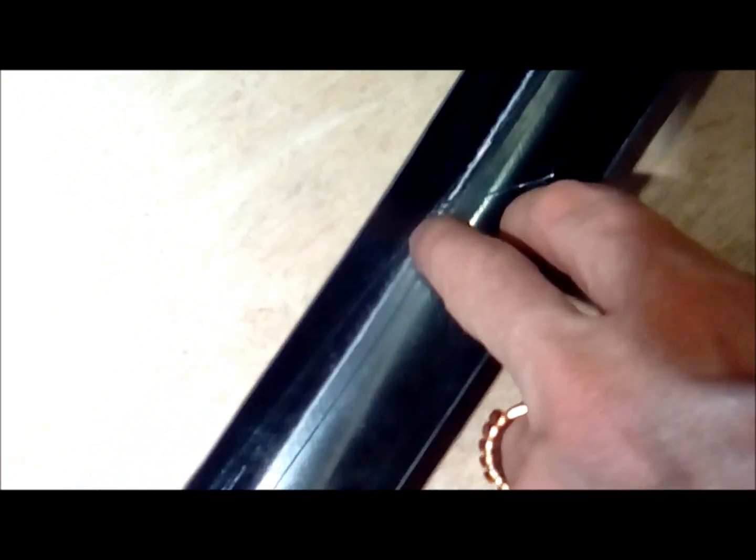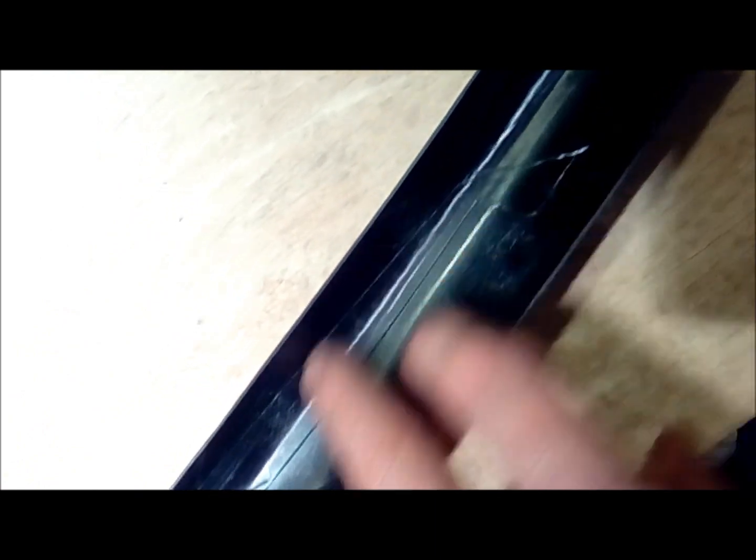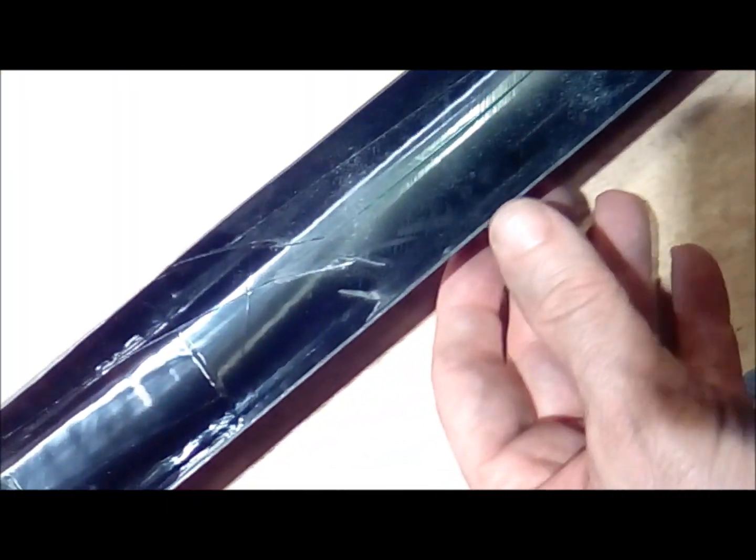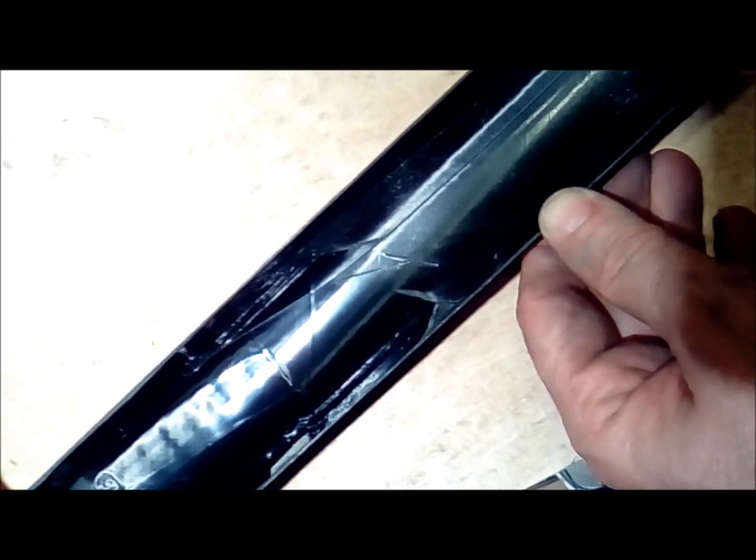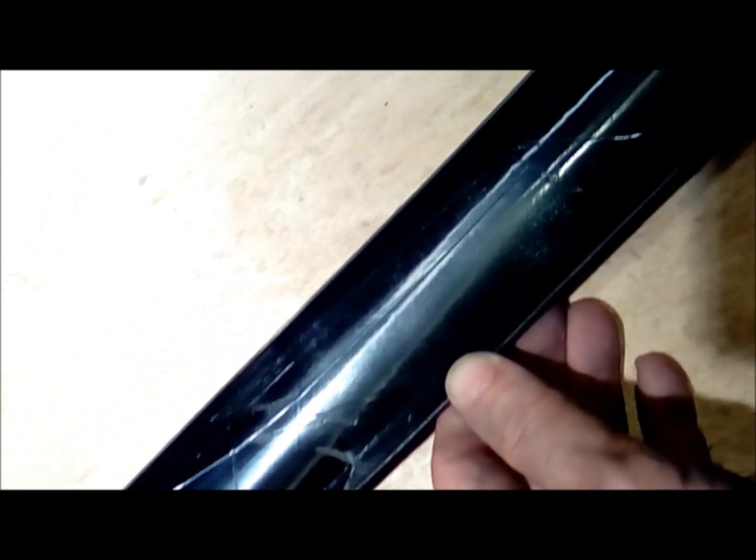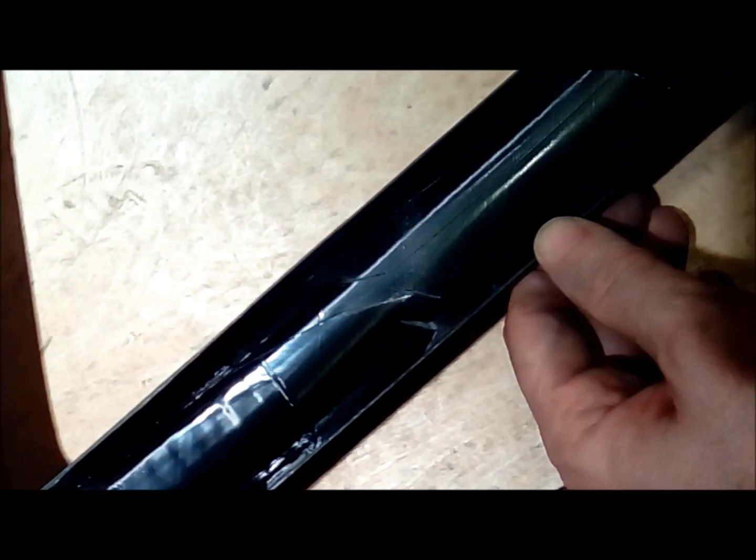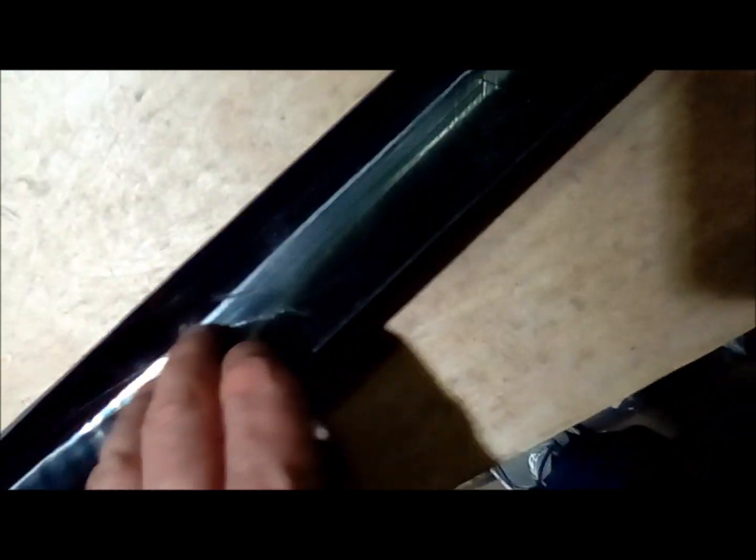For the most part I see, the only complaint I would have about this frame is that there's these long longitudinal wrinkles which I can't decide is just whether it's just resin or whether it's actually wrinkle in the carbon fiber. The way that these happen is they'll be a bladder in here, right? And the bladder gets inflated to compress the laminate while it's curing to get rid of all the, you know, make sure you have a consistent carbon resin laminate, make sure you eliminate any voids in there. So it doesn't always compress cleanly at the surface and you can get these wrinkles inside of there.